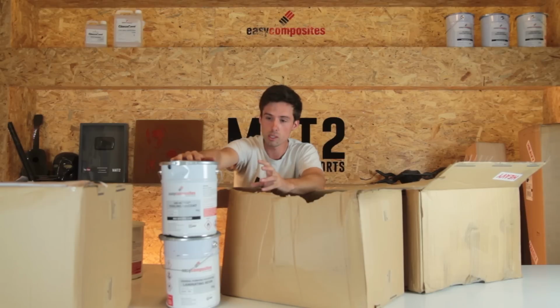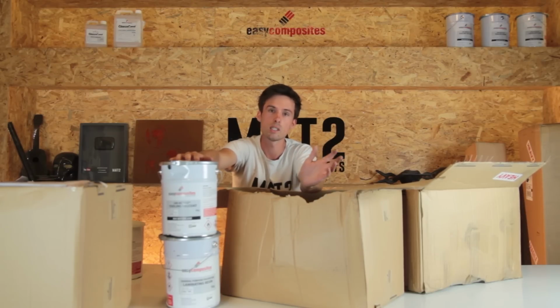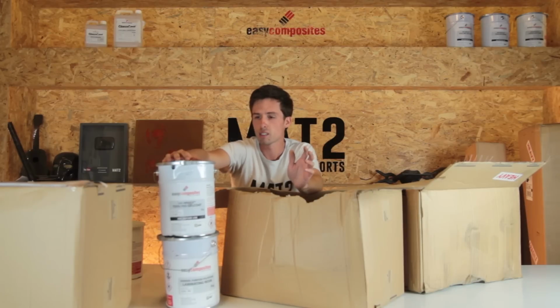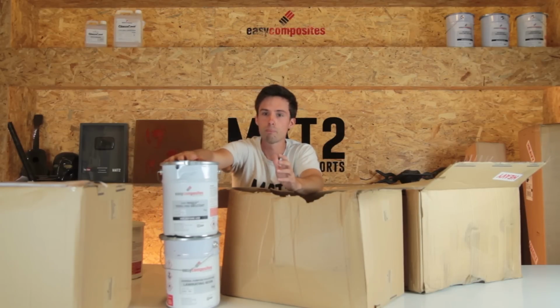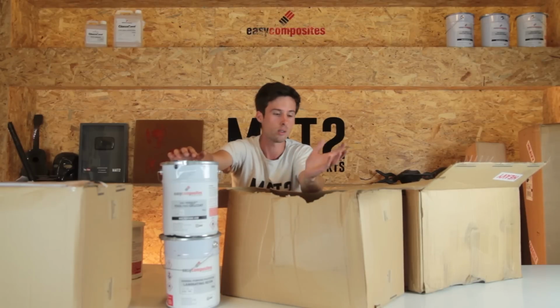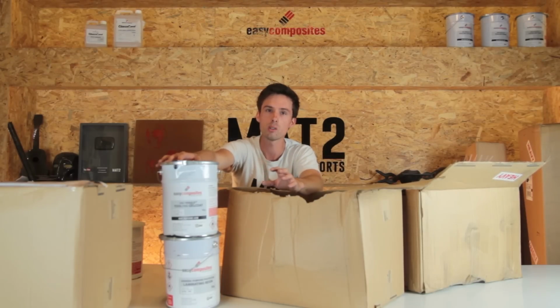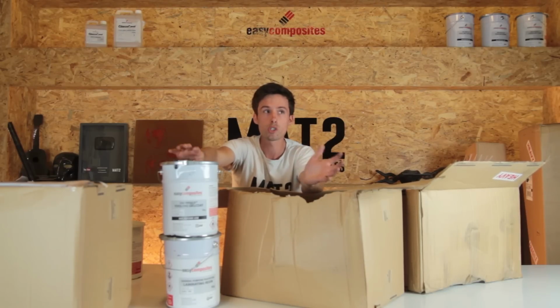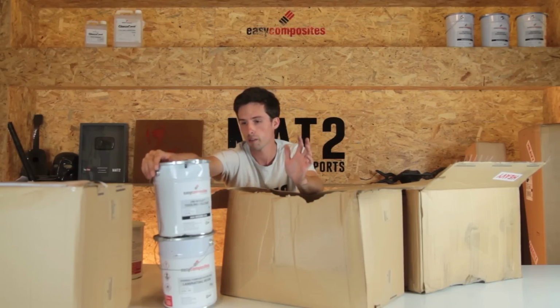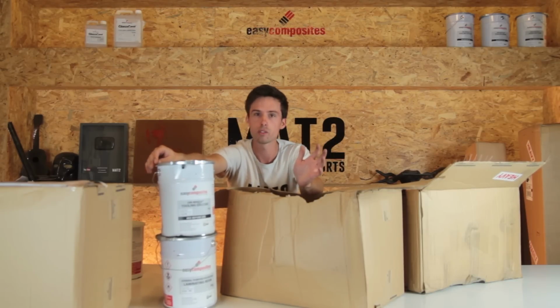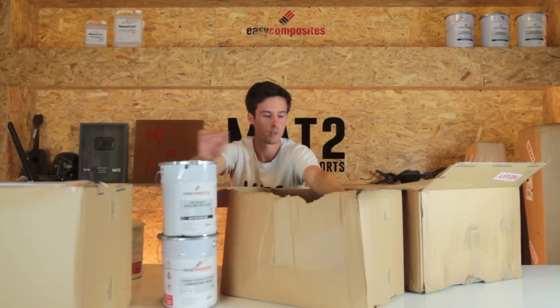So that's their Unimould system, and I tend to always go for that system when I'm making molds for customers or for the tutorials, as you could have seen in previous tutorials, because it's a stable resin. You can make a mold, I would say, in 1 day, and then just let it cure for a few days, and then you're sure you have a good mold. And worst case, you have some little repairs to do on the gel coat, but you're sure that the mold is stable, it will not warp or shrink or have some inconvenient problems after demolding. So that's why I'm always going for that system.